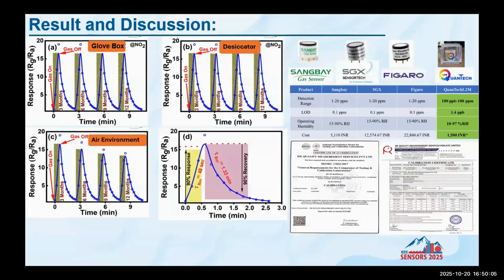And these are the sensing results. After that, I used the same transfer process for each of the 3 samples, kept in the glove box, desiccator, and air environment, and measured the gas sensing response. Significantly, I found that the sensing response decreases for the samples kept in the lab environment or open air environment.